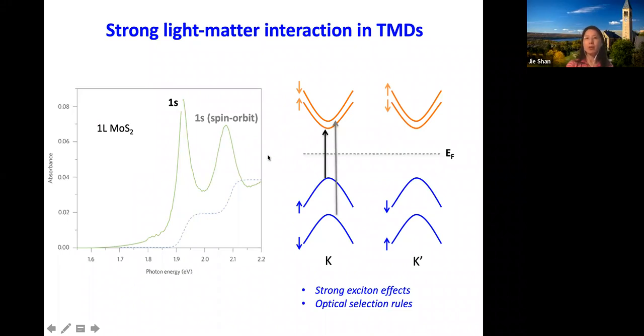The monolayer semiconductor interacts very strongly with light. This is a spectrum of monolayer absorption, and you can see very strong peaks. This is due to electron-hole interaction, and they form excitons. Otherwise you would just see a step-like transition due to the joint density of states. This peak can be almost 10%, so each monolayer can absorb 10% of a photon at resonance. You will see a little later in the talk that this gives us a lot of sensitivity if you want to probe the system.